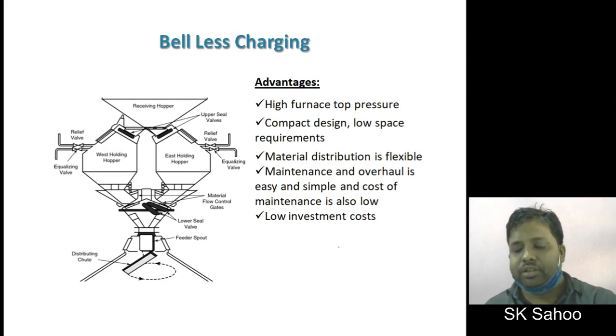So nowadays we generally use bell-less charging system in almost all furnaces. In case of bell-less charging, there is no bell, but there are hoppers and a distributing chute which distributes the raw materials into the blast furnace uniformly. Bell-less charging is considered to be one of the modern trends in blast furnace due to some advantages over bell charging system,